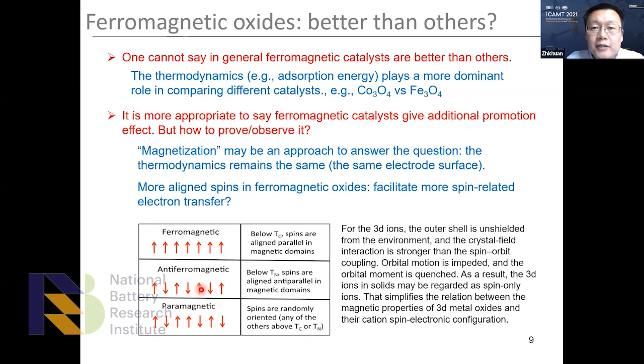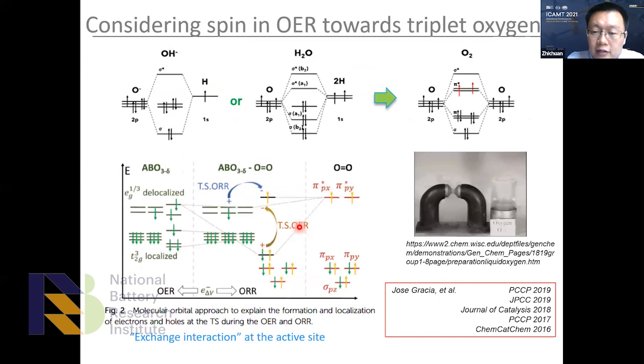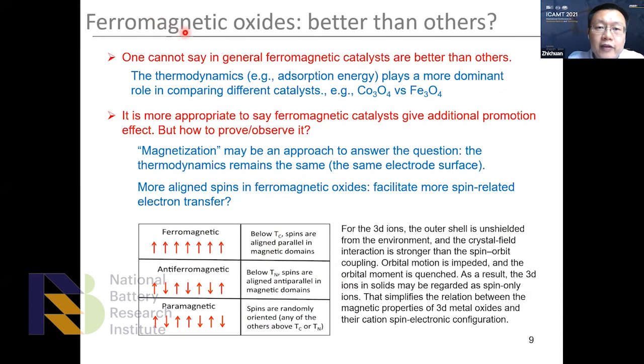I cannot say so because, for example, I can give you one example: cobalt oxide and iron oxide. Cobalt oxide is much better than iron oxide in the OER, oxygen evolution. However, iron oxide is a ferromagnetic material, and cobalt oxide is an antiferromagnetic material. So this actually goes against the conclusion we drew purely from the modeling. The question is, how can we prove that additional benefit? As pointed out here, triplet oxygen formation needs spin-selected electrons, and this is the additional benefit given by the ferromagnetic oxides.